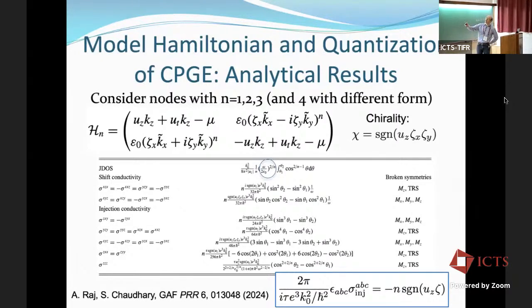And so we worked out, for this effective low energy Hamiltonian, charge n equals 1, 2, and 3 for the nodal point, that's the topological charge, with chirality given by this expression. U is the tilt of these Weyl points, and here is appearing as the exponent of the off-diagonal elements, telling us about the magnitude of the charge. And you need to break certain symmetries in order to get non-zero responses in these various components of the second order tensor. The key thing here is this expression, that if you sum over a particular combination of the injection current conductivities divided through by some non-universal value such as the relaxation time, then you get a universal result.